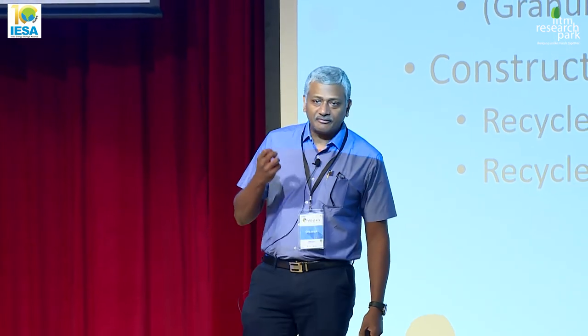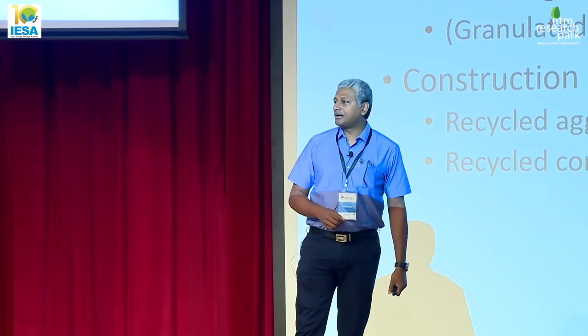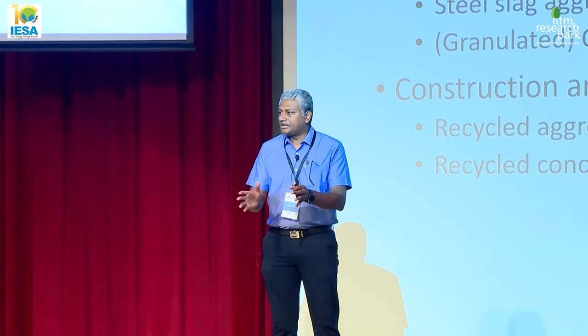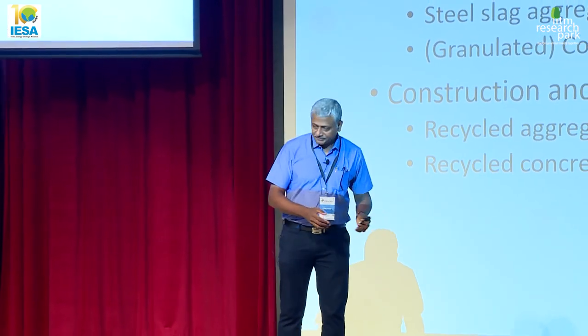If you can air-cool it, the slag becomes more and more crystalline, and because of this, it does not have much reactivity in it. This has good potential for use as an alternative aggregate in construction. But again, the quantities are limited by the extent of slag that is available.